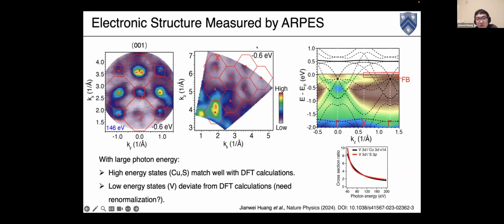Then we took the ARPES data on this compound. We find that actually the high energy bands match very well with the DFT calculations, which come from the copper and the sulfur bands, but the low energy bands deviate from the DFT calculations, which are from the vanadium bands.